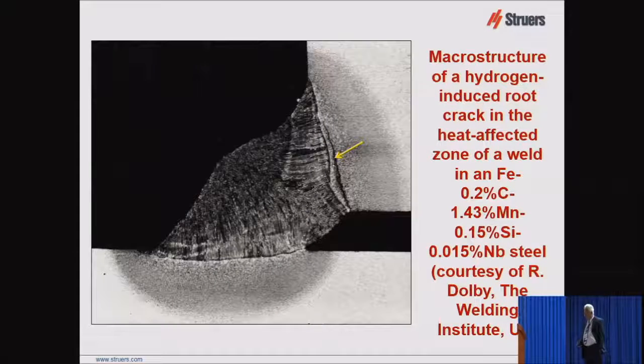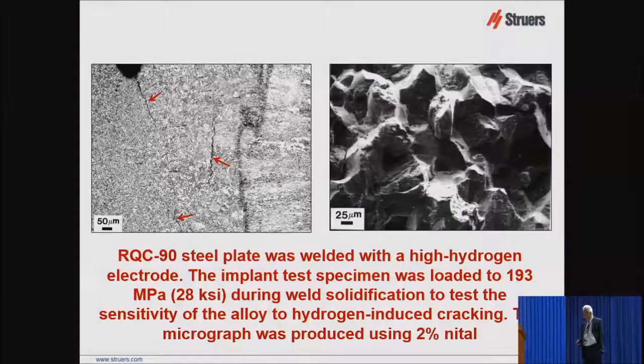Here's an interesting weld. This picture was given to me by Dr. Dolby at the Welding Institute in the UK. It's a macrostructure of a hydrogen-induced root crack in the heat affected zone. This is the alloy composition, 0.2 carbon, 1.43 manganese, 0.15 silicon, and niobium addition. And you can see there's very little weld penetration into the base metal here, which is not good. And there's this big gap here, which is also not a very good thing to have. But of course, we have this crack here as well. And there's a crack on the bottom there.